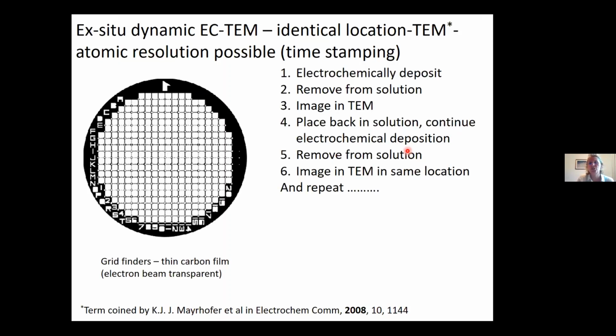So what you do is you will take your grid, and people tend to use the grid finders. So you can look in a particular location, you do your deposition, you remove from solution, you put it into your highest resolution TEM. So you're now operating under vacuum conditions, you image, and then you go back and you look in exactly the same place and you image under exactly the same conditions. And you keep repeating that process in order to get these timestamp dynamic information time shots.